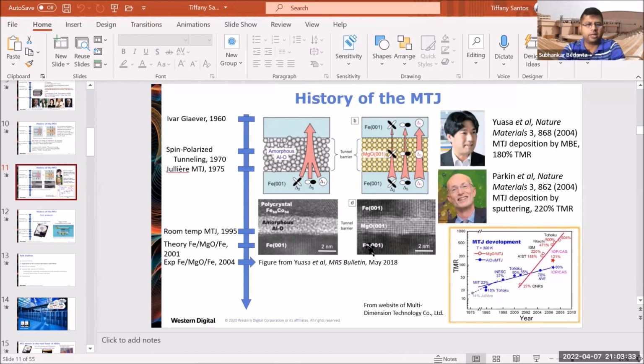Yeah, so basically the MgO is now the best spacer for TMR, isn't it? Yes, it does give you the higher TMR values. Now, folks can think of novel materials that will also lend themselves to this spin filter effect. For example, some spinel barriers, there have been some nice demonstrations of high TMR with those as well. They are more challenging to make high quality, and especially in a manufacturable way. But there are other materials that can also lend themselves to this filtering effect.